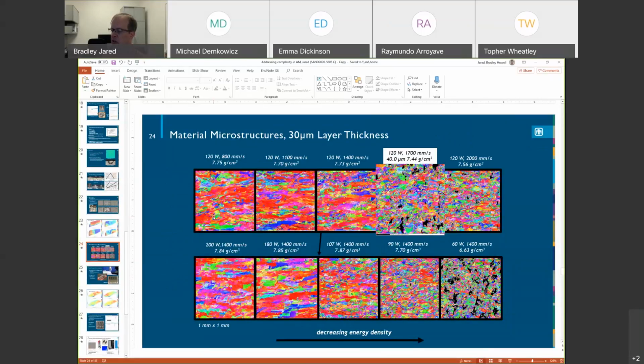Absolutely. So if you look at this, hopefully you can see my slide here. If you look at, say, the left 3 or maybe 4 images on this plot, these are all different set points on the machine where we're getting different grain structure. We're getting basically fully dense material, right? Again, there's sort of an inherent porosity in some of this that it's really difficult to get all of it out. But this is what I would consider good material. So in those sort of, say, 6 to 7 or 8 images, microstructure set points, we're going to get a distribution that's going to have probably the same span or width, but the averages are going to be different, right? We're going to have higher ductility in one or higher yield strength in another, right?